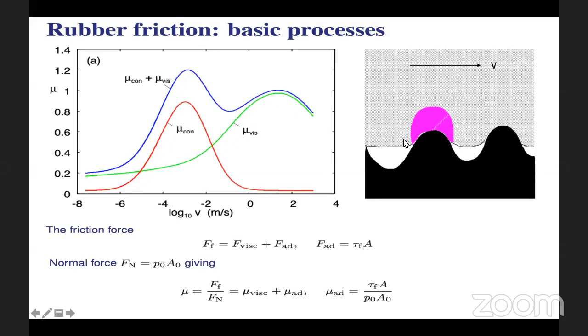different contributions to friction. So the friction force is a combination of a viscoelastic response, F visc, and a force term which is due to adhesion. In adhesion, if you consider dry sliding, where there is no lubricant present at the interface, then this adhesive contribution to the friction force is the shear stress times the area of real contact. So the adhesive friction basically arises because of the shearing of the area of real contact.